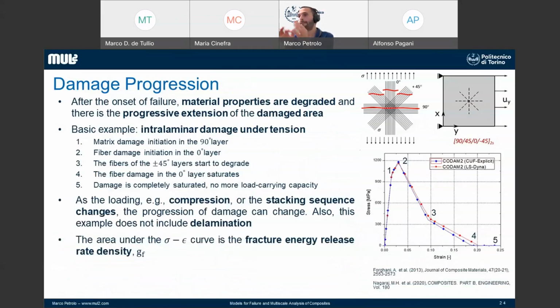So with the failure index, you can detect where the failure takes place. Then you need to study how failure can progress. So now we talk about damage progression. As you have the first point in which failure takes place, then failure can increase. So we have a propagation of the failure. And that's what we mean by damage progression: the ability to track failure and to see how a failure area propagates into the composite structure. This is a very difficult phenomenon to model. This is a nonlinear analysis because we have a degradation of the material properties. So you need a nonlinear analysis to take into account this kind of phenomenon.